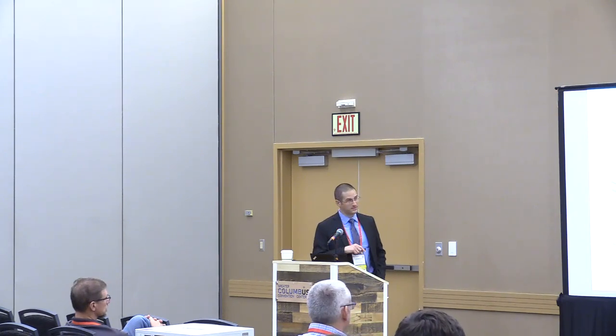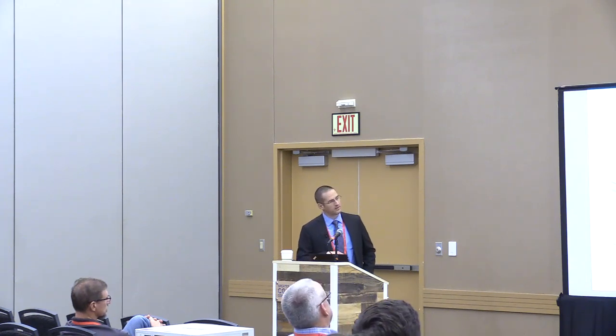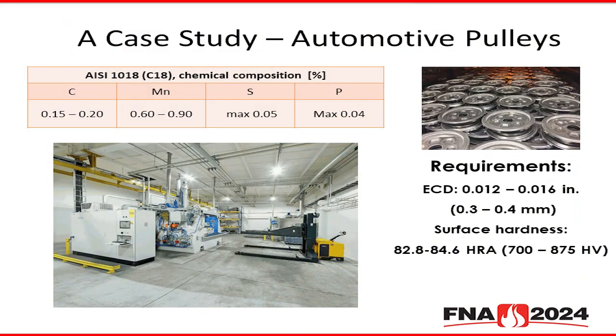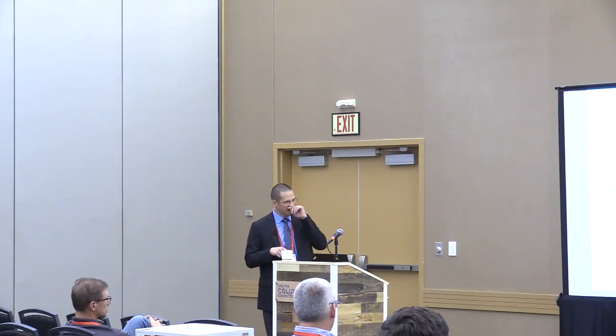The parts in this case are typically carbonitrided in an atmospheric furnace. The requirements are for roughly a 12 to 16 thousandths case depth and a target surface hardness of between 700 and 875 Vickers, or roughly 83 and 84.5 Rockwell.